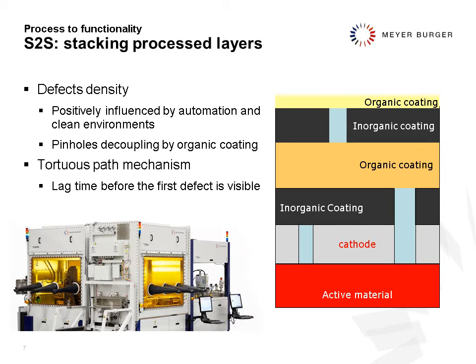So why does it happen, and why do we want to do such stacking? Well, the reason is because of defect density. Defect density of inorganic coating, which are ideally perfect barriers. If you don't have any defect, you can have a single inorganic coating overall and you will be fine. But reality is that there is a density of defects, and it can be very low. And in fact, you can influence it by using automation and using clean environments, but it's impossible to bring it to zero and be certain of it.